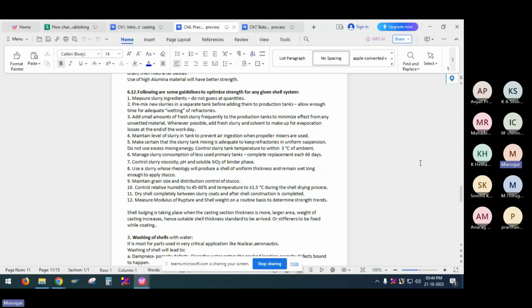Control slurry viscosity, pH, and soluble SiO2 binder phase. In the binder phase, use a slurry whose rheology will produce a shell of uniform thickness and remain wet long enough to apply stucco. Maintain grain size and distribution control of stucco. Control relative humidity to 45-60 and temperature plus or minus 1.5 degrees during the shell drying process. These are just tips which will help to have a uniform and consistent quality in the final product.